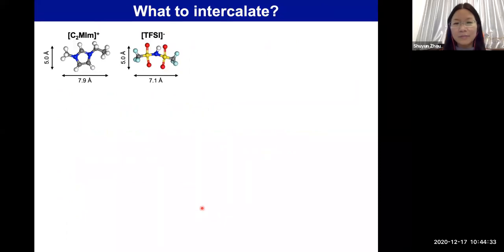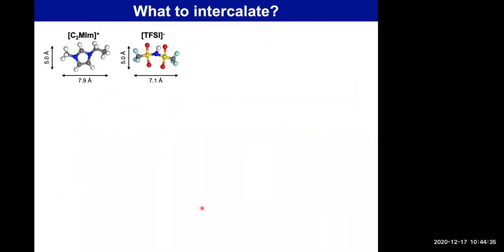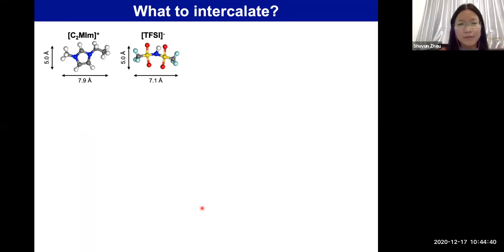So let's first look at the ions that we choose to intercalate. We first start with the ionic liquids. Here I show you the cations and anions of a very typical ionic liquid. This kind of ionic liquid has been widely used for interfacial gating to inject charge carriers into layered materials. But here we'd like to intercalate these large ions into the van der Waals gap.